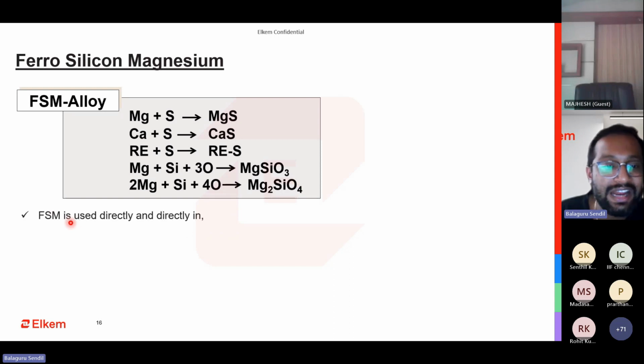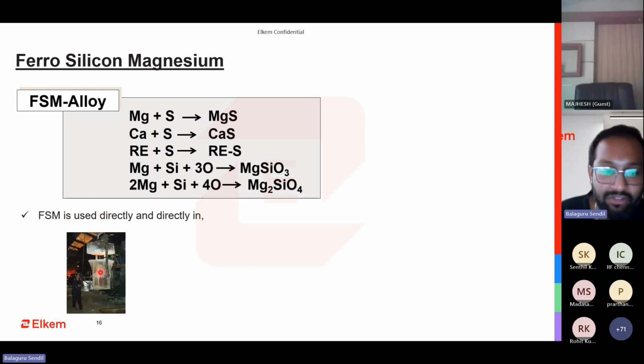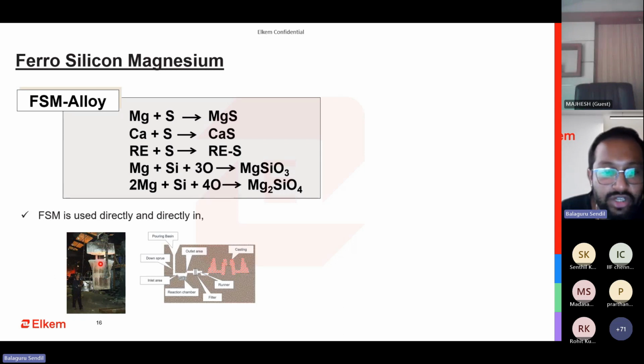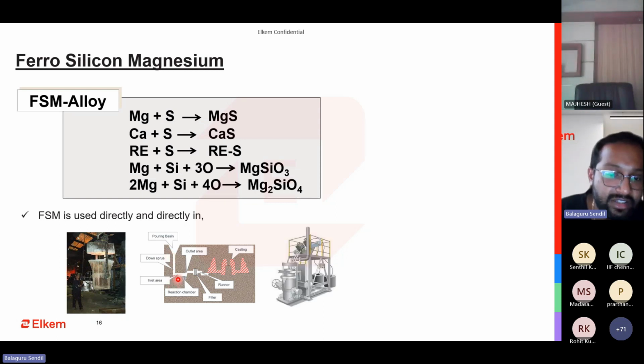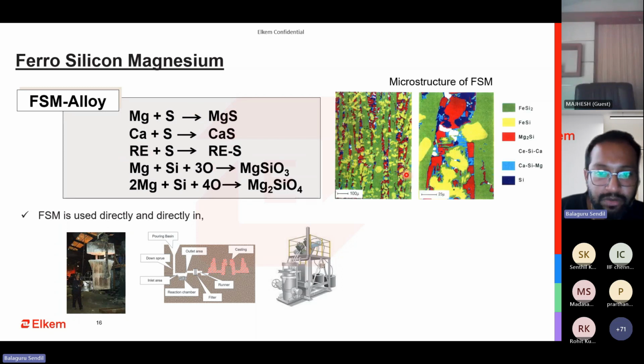So FSM is directly and indirectly used where we have ladles. We have different types of ladle: open ladle, tundish ladle, pocket ladle. In all of these, we can use ferrosilicon magnesium. In the in-mold ferrosilicon magnesium treatment, in-mold FSM treatment, there also we are using ferrosilicon magnesium. Interestingly, in cored wire also people use ferrosilicon magnesium. The wire, what you see inside, has some amount of ferrosilicon magnesium fines inside it. Because if they use pure magnesium alone, it will be very difficult to get the reactional advantages that you're getting here.